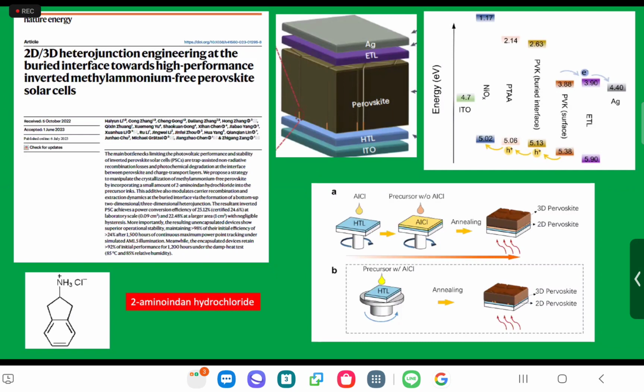If you take aminoindane hydrochloride, it makes a 2D perovskite with formamidinium and methylammonium cations. And if you add this in the starting solution of the perovskite, in a very small amount, just 1 milligram per milliliter, it does direct the growth of the perovskite. So how is that possible?